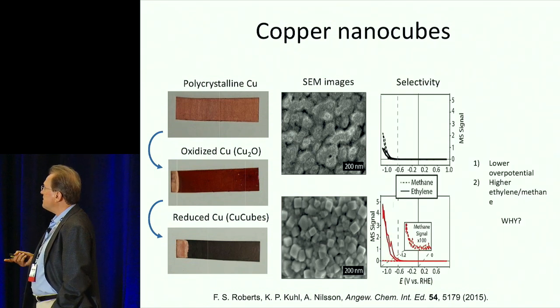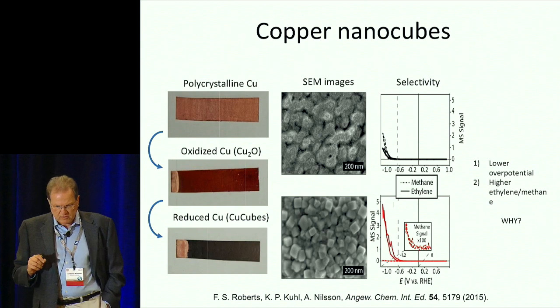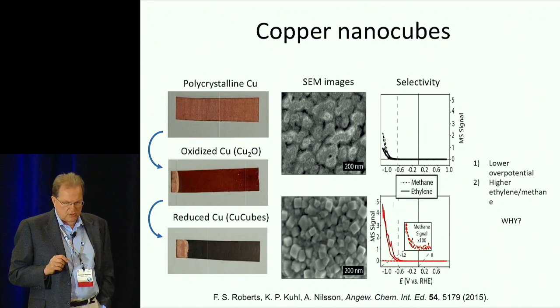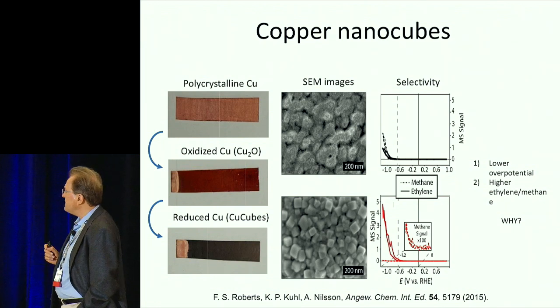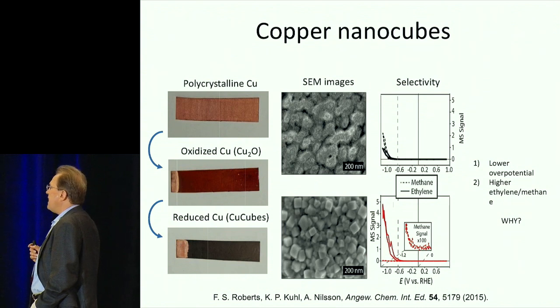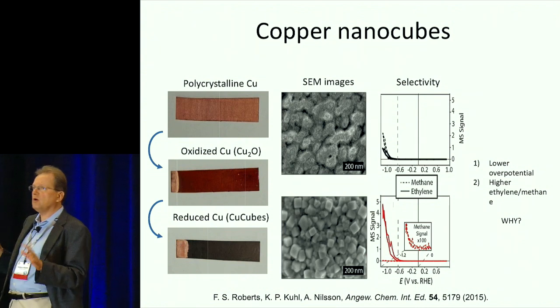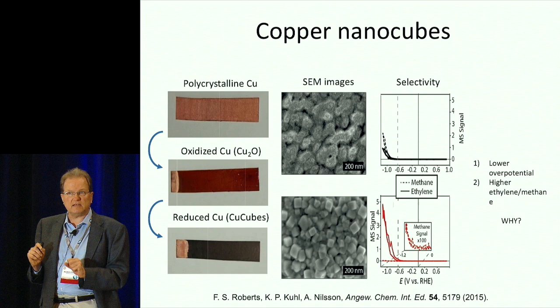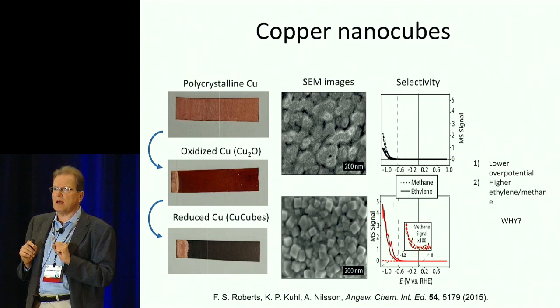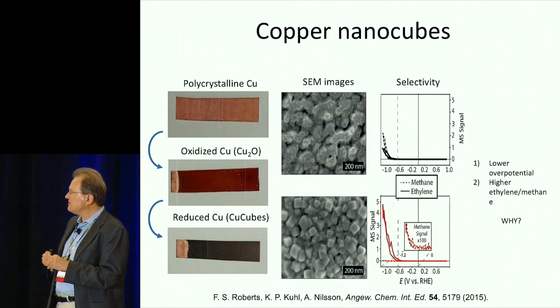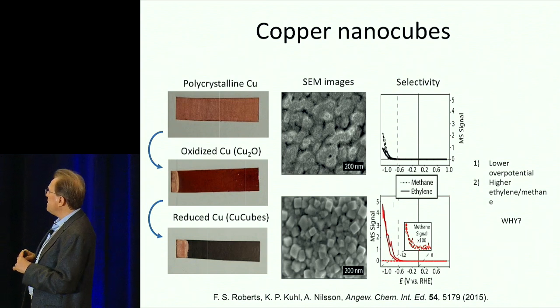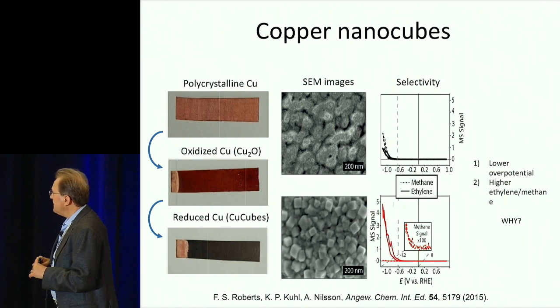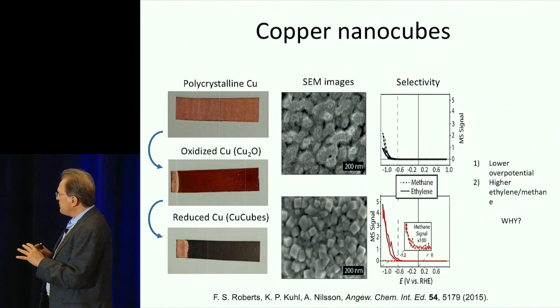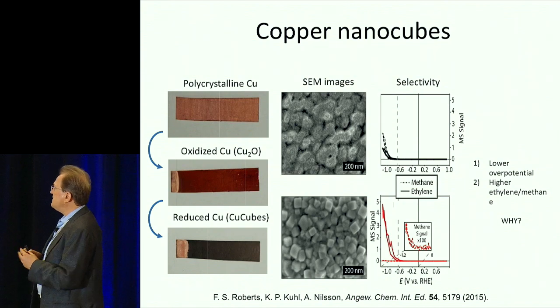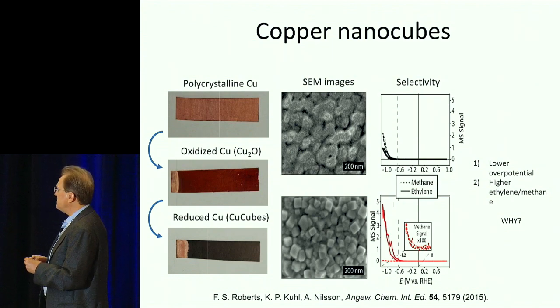And it turns out that in this experiment, using an online mass spectroscopy measurement, it had a very high selectivity for forming ethylene compared to methane, although we don't know the total activity, which is something we are measuring right now in collaboration here at Stanford with Tom Jaramillo and Chris Hahn's group, but we are detecting all products. But we are seeing this very interesting change in selectivity.